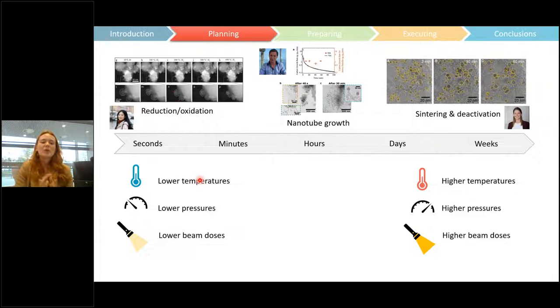Just because you're in the wrong location on this time span doesn't mean you can't run your experiments. If you have very fast reactions, you can use slightly lower temperatures, that might help. You could use lower pressures if you're 100% sure you have no leaks. And you can also lower your beam dose, which might help to slow the reaction down. Whereas if you have reactions that will take a long time, you can increase your temperature, your pressure, and your beam dose. So it's a good idea to think about how you're going to modulate the length of time of your reaction and how you're going to capture that.